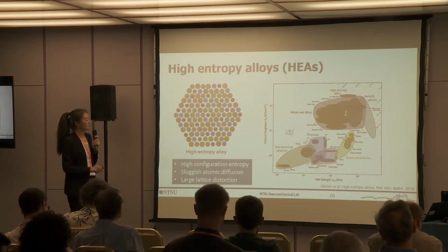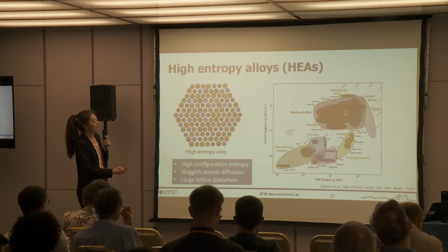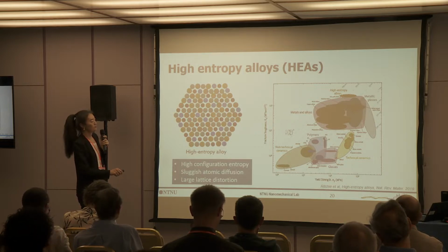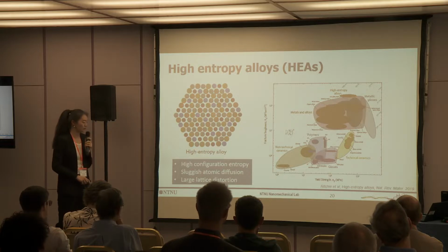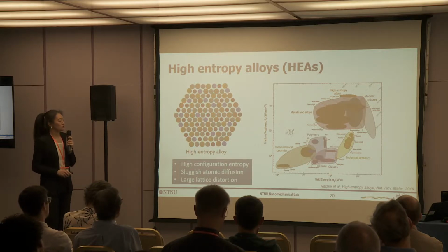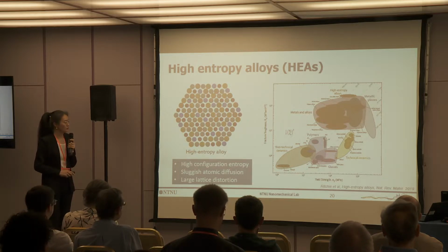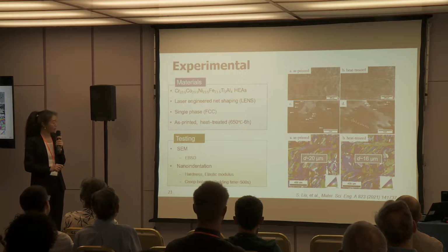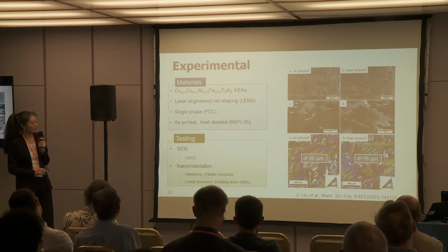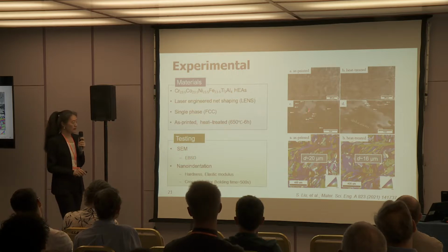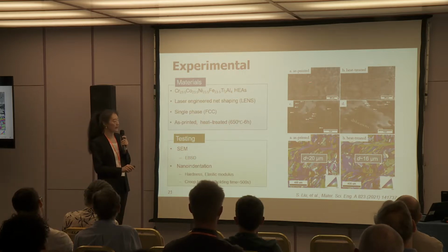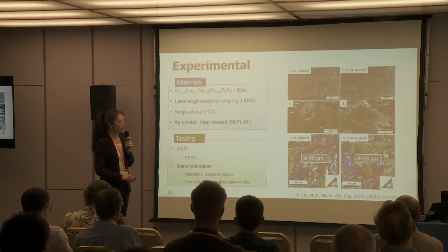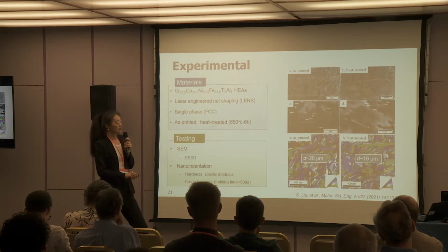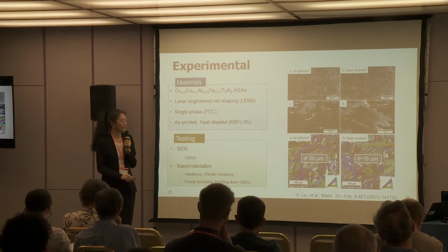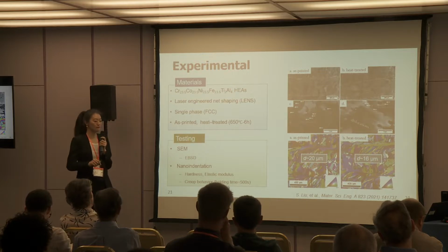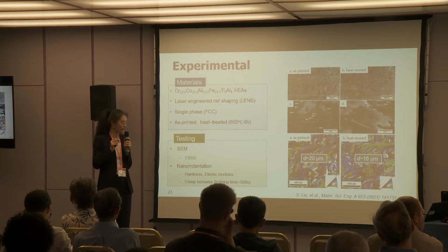Here I borrow a figure from Professor Ritchie. You can see the comparison of the high entropy alloy here with other materials. Its property is superior to many other materials, and this attracted a lot of attention to use high entropy alloys for different purposes. In our case, we print the high entropy alloy with mainly these 4 elements, and we got this FCC structure. Here are the micrographs, and you can see the printed layer structure, mainly with a columnar grain shape. The as-printed and heat-treated materials have slightly different grain size, but this will not influence our results since we only focus on a very tiny deformation volume, mainly in the individual grain.